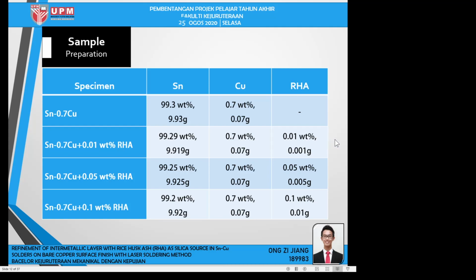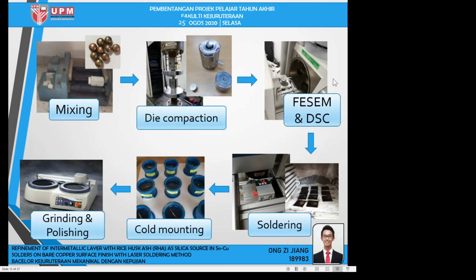So this table shows the preparation of the samples for the ratio of tin, copper and RHA for 4 different weightage percentages of RHA. As you can see, the copper weightage percentage is fixed, and the RHA varies from 0% to 0.1%, and the remainder is tin.